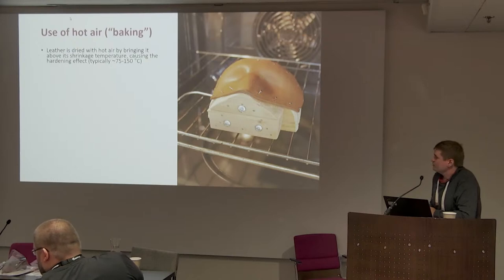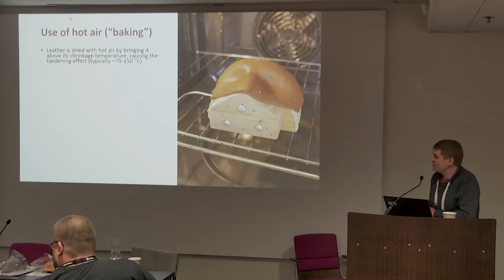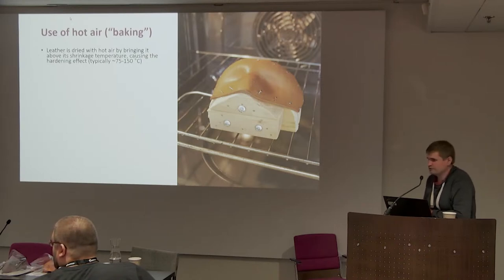But modern material testing with baked samples hasn't been very convincing, and it has led me to believe that, at least when used as the sole hardening method, this is not actually a viable armoring method either. Perhaps when you combine it with several other things we have already discussed, like multi-layered structures, animal glues, and gesso and varnishes to make it a stronger structure, then baking may have some viability, but not as a straightforward wet the leather and dry it in an oven. It won't produce very convincing armor.